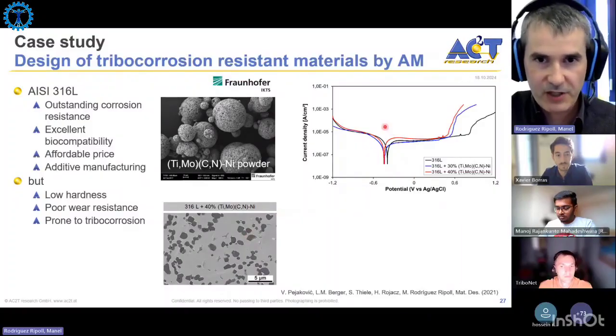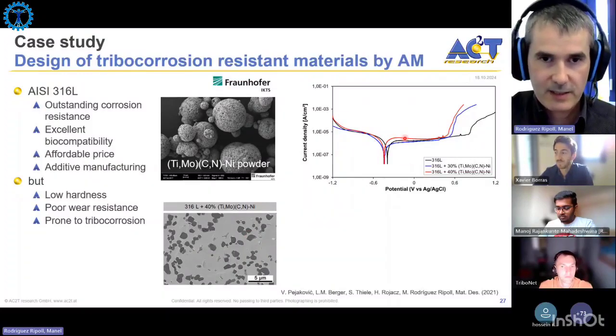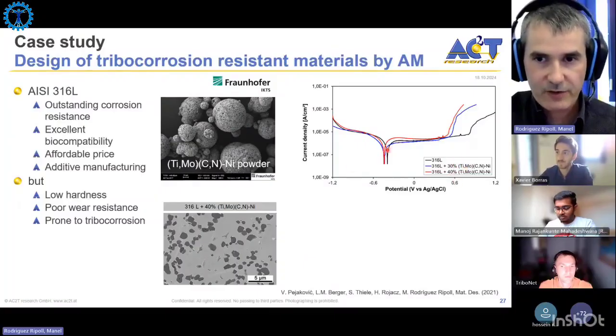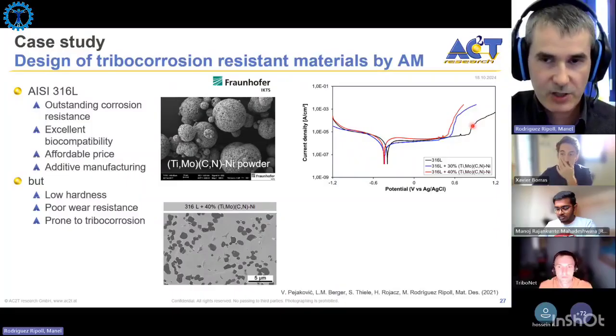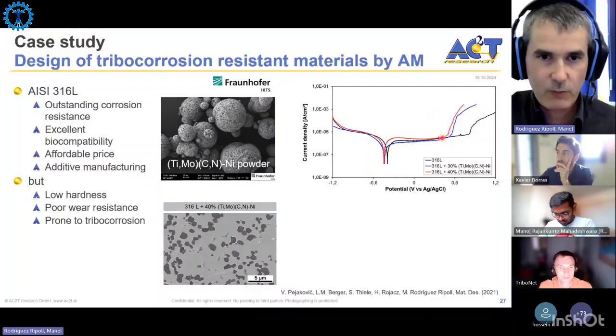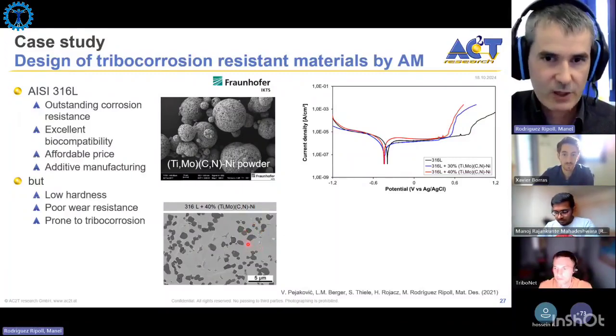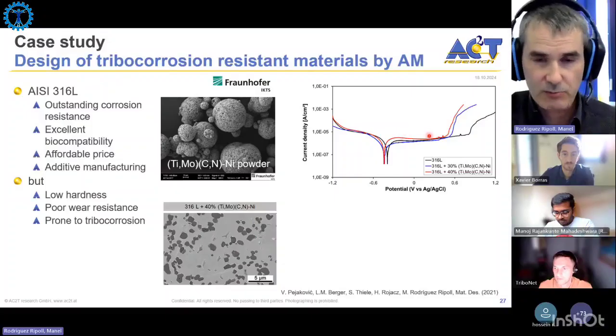So we are not rubbing anything here yet. So this is just the polarization curve. And we see that this material, 316L, has a passive domain, and these other ones containing 30 and 40% of titanium carbonitride inclusions, they still have a passive domain. The only price to pay is that the transpassive potential, so the breakdown potential, shifts towards cathodic values. It means that this material will be a bit more prone to pitting, because of course you have some defects, and these defects will be initiation sites for localized corrosion, but still you have passivity, so this is quite good.